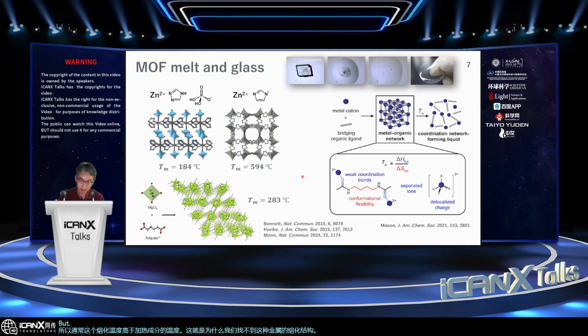But back to around 2015, our group and one group in Cambridge, almost at the same time, found specific metal organic framework crystals that melt by heating. This case is made of zinc and this molecule, and has a two-dimensional structure. You can also see the images. This is a single crystal of this zinc compound. But if we heat it, it forms a very stable liquid without decomposition. And then the melt can be quenched, and we can also get this glassy state.